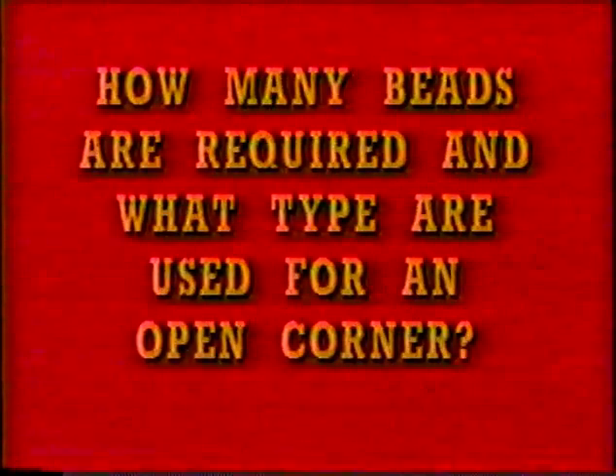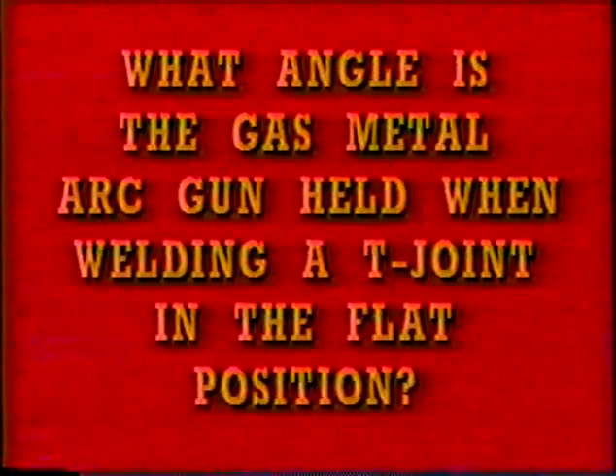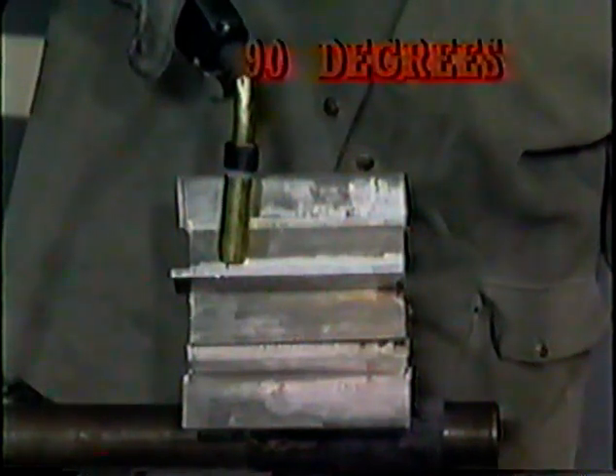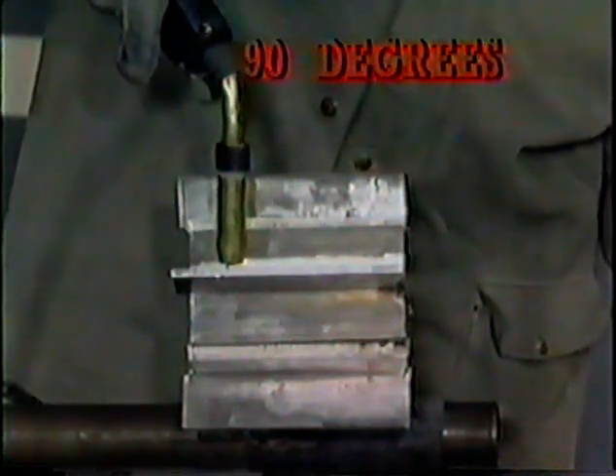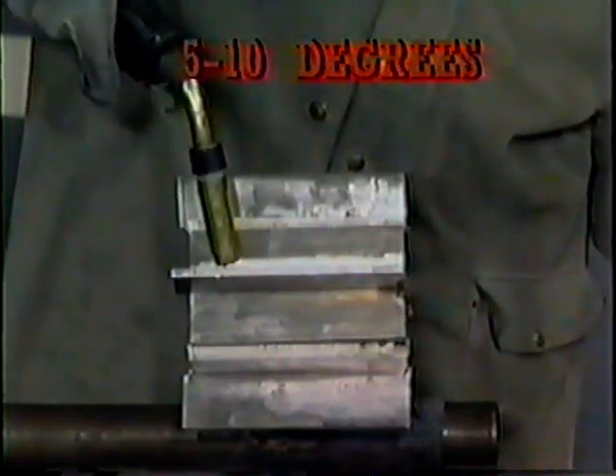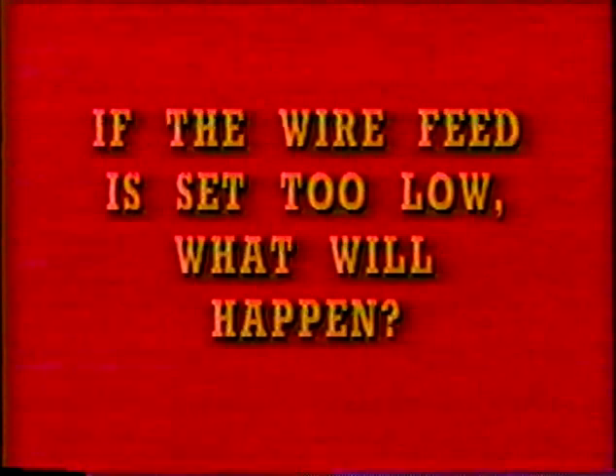Now, let's review. How many beads are required and what type are used for an open corner? The answer is 3. 1 is penetration, and 2 and 3 are weave beads. What angle is the gas metal arc gun held when welding a T-joint in the flat position? The answer is 90 degrees to the work and 5 to 10 degrees away from the direction of travel. If the wire feed is set too low, what will happen? The wire will burn back into the contact tube.